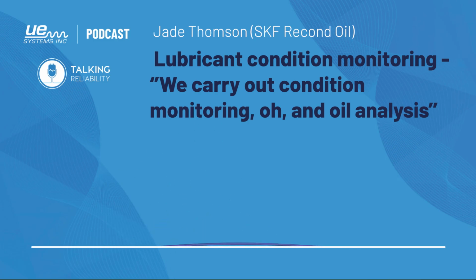But using this type of post-failure analysis won't give us a massive amount of trends and information, but it will give us something to learn from, because we can then use these ratios of wear that we see to compare it to other gearboxes that are the same on site. This again was the public sector. It was something where public are using these assets quite frequently. It wasn't rail, this one, luckily. But what this allowed us to do was then apply this knowledge as alarm sets to the rest of the assets, so that we could see the ratios before a catastrophic failure occurred. Hopefully that makes sense to everyone.